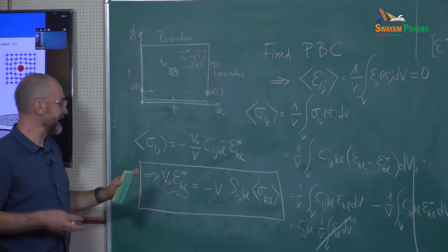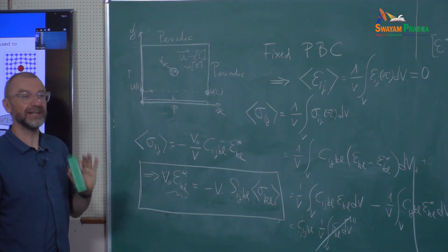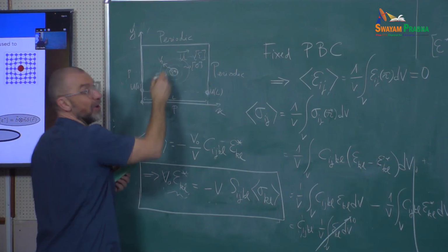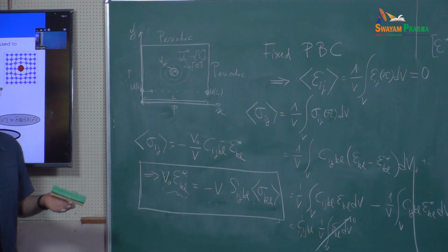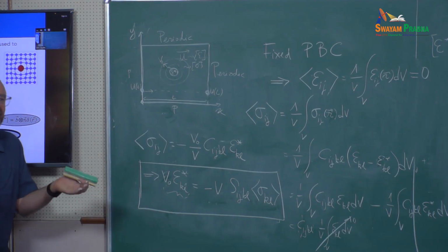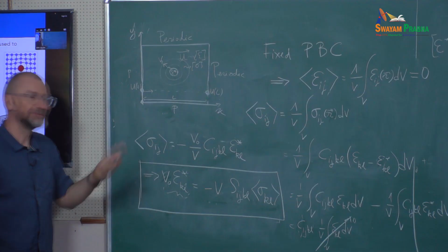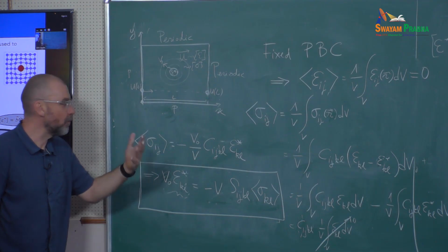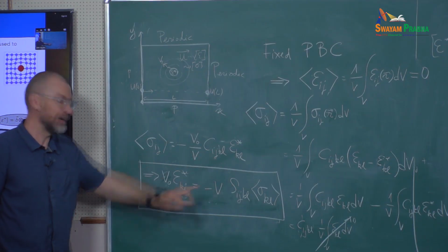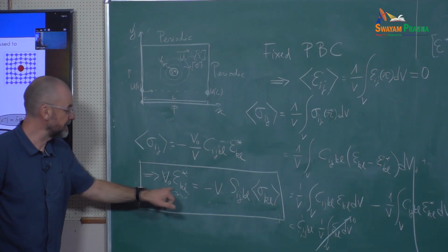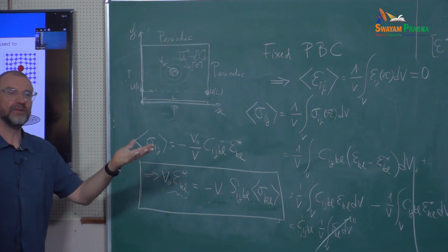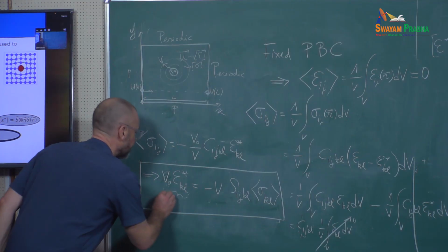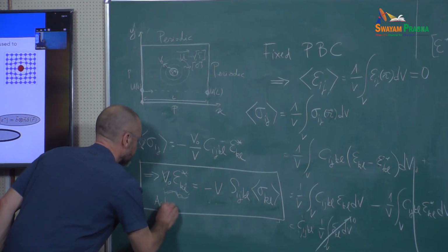Yeah, but in the elastic framework, it does. So the bigger the volume, the smaller the equivalent eigenstrain I will have inside my object. As I said, what is really well defined in that framework is the product of V naught times this. And this is equivalent to an activation volume actually, to use words connected to other fields. This is an activation volume.